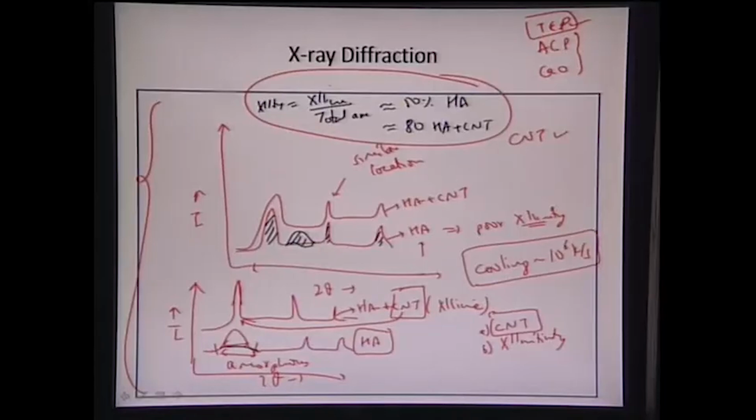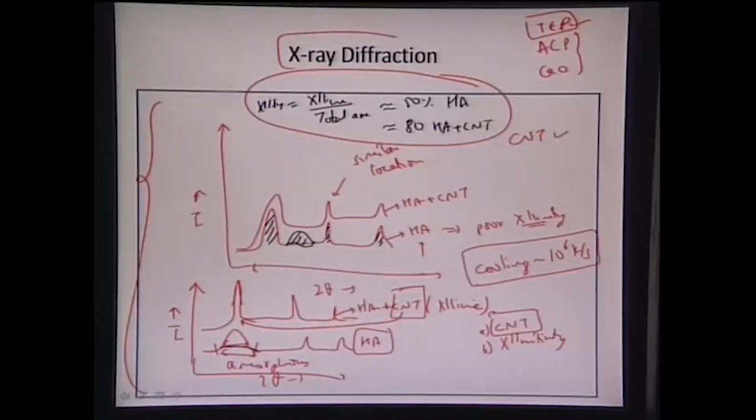of carbon nanotubes. And at the same time, we don't see any CNT peaks in the X-ray diffraction, because the overall hydroxyapatite peaks are much more dominating, and depending on the concentration of CNT, they may not just appear. So that is the overall deal with the X-ray diffraction.